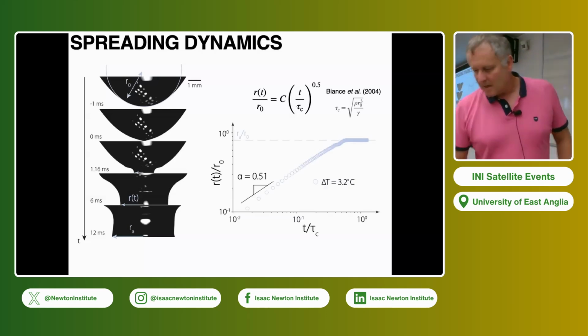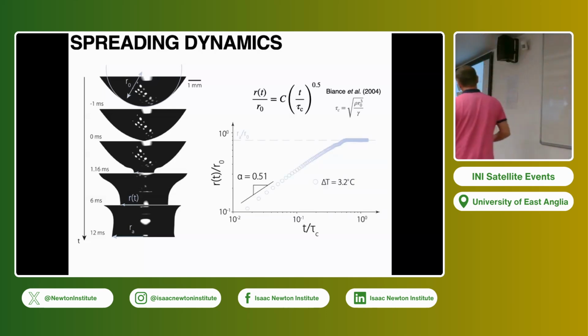Does it work well? Actually, if you take delta T equals 3.2 Celsius degrees, you have a very nice scaling law, in good agreement with the square root of time, and we are in a log-log plot. Everything happens as if the drop was spreading like the square root of time, and in a very rapid zone, you suddenly stop. So as if you expand at the square root of time, and then suddenly you are stopped by some mechanism.